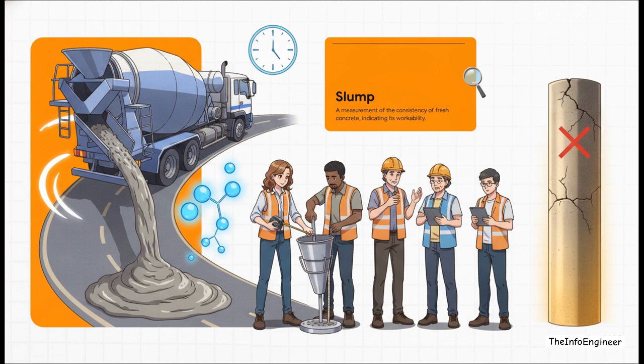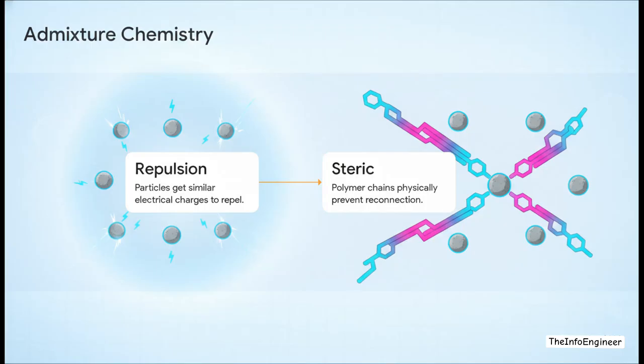So, if you can't add water, what do you do? This is where we get to see molecular chemistry on demand. Instead of water, plants pump in super plasticizers, specifically polycarboxylate ethers, or PCEs. These molecules do two pretty amazing things. First, through electrostatic repulsion, they give the cement particles similar electrical charges so they physically push away from each other, which releases trapped water. Second, through steric hindrance, they use these long polymer chains that act like microscopic brushes to physically block the cement particles from clumping back together. The result? You get highly workable, freely flowing concrete without adding a single extra drop of water.